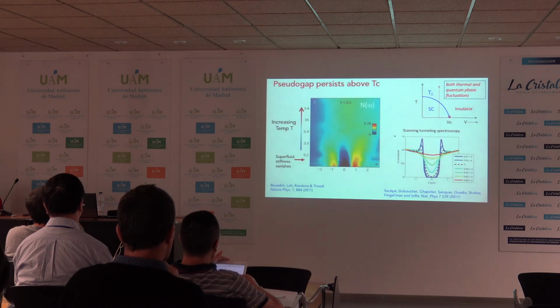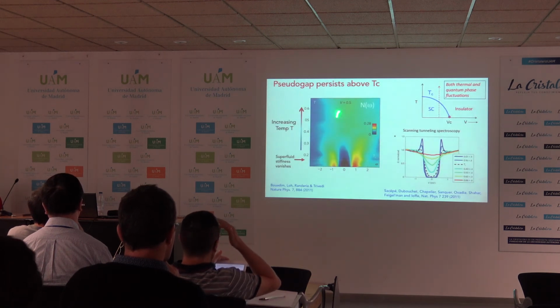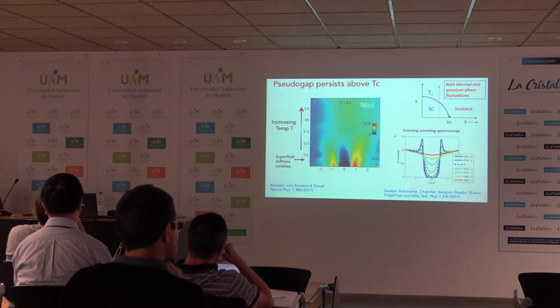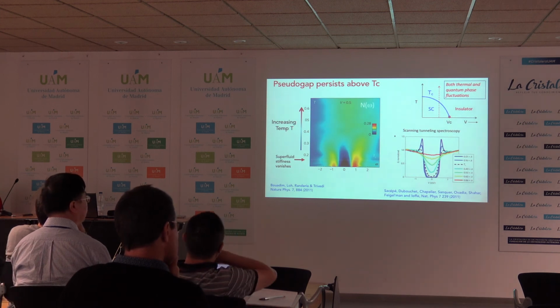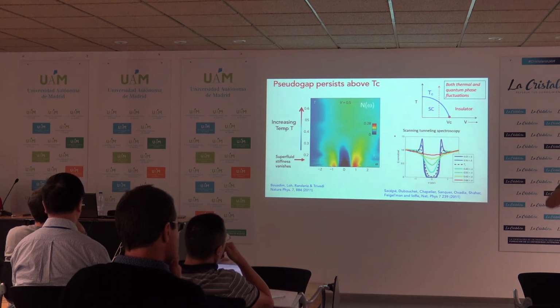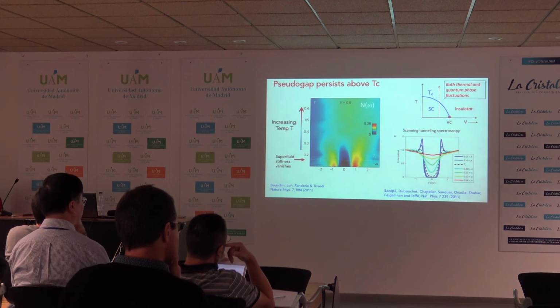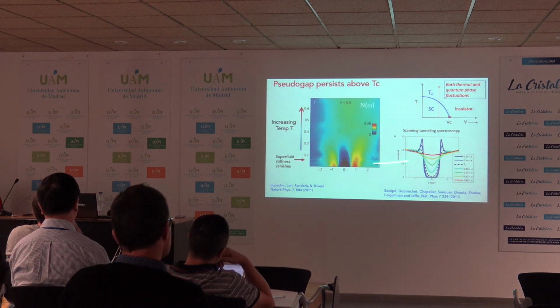This one, right? So here at finite temperature, it's a 2D system. The transition would be a Kosterlitz-Thouless transition due to the unbinding of vortices. And in that case, the superfluid density has a jump. And that's what we calculate. So we don't see a jump because of the rounding in a finite size system, but you can make that linear 2/pi Tc plot and get Tc from that. And that's how these white transitions were obtained, basically applying finite size effects on the Kosterlitz-Thouless transition.